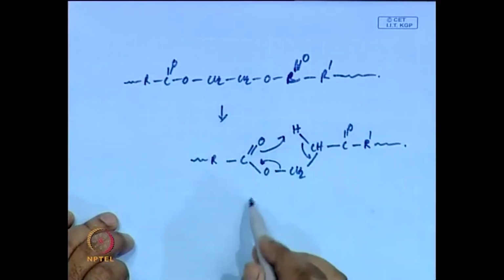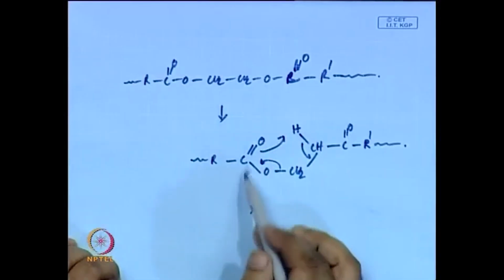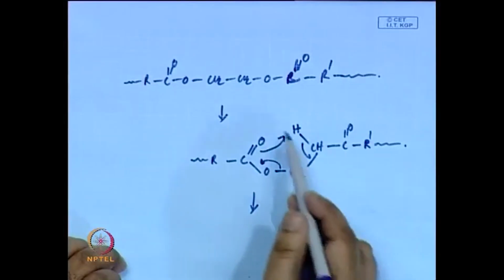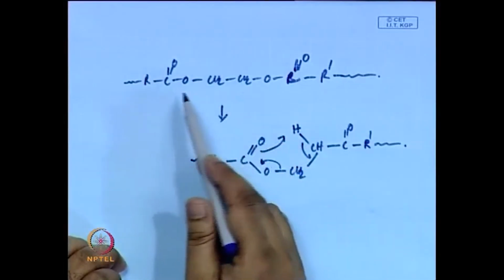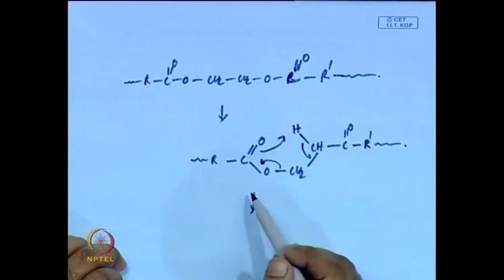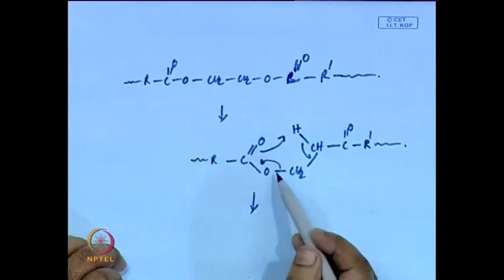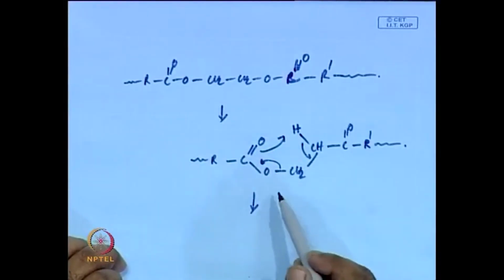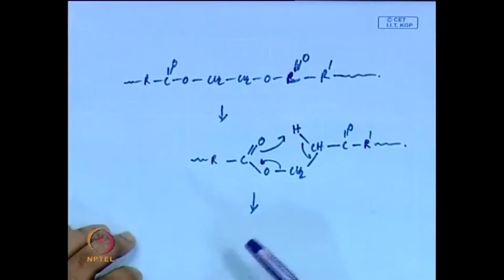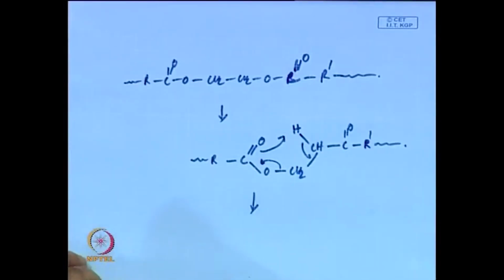With this you can generate a free acid group and an alkene group here. This is very common if you have a beta hydrogen present; by a 6-membered concerted reaction, it might do a side reaction and you can end up getting new functional groups or new products which might give you color at the end of the reaction. So, that is one example.